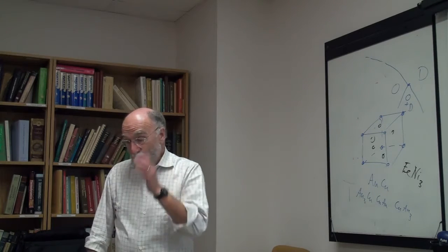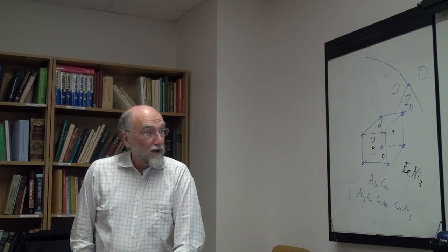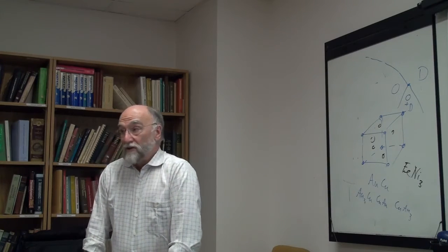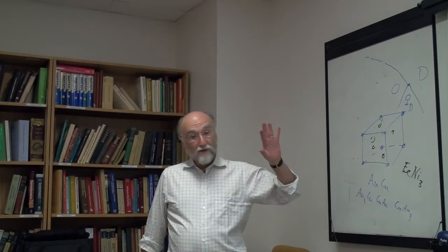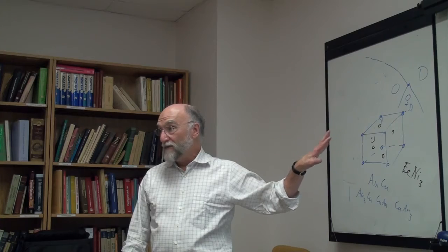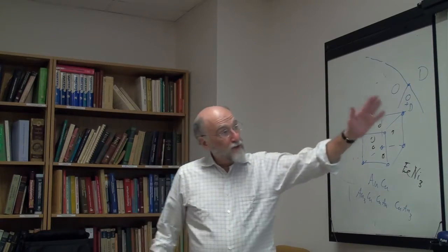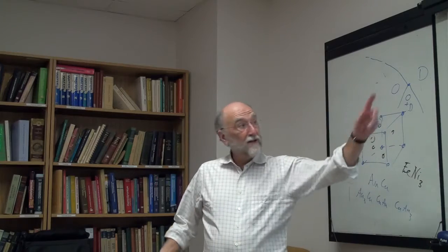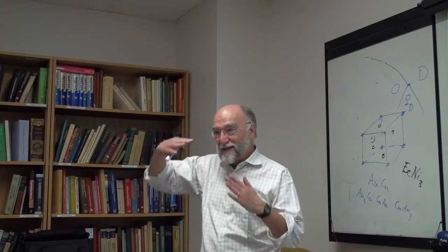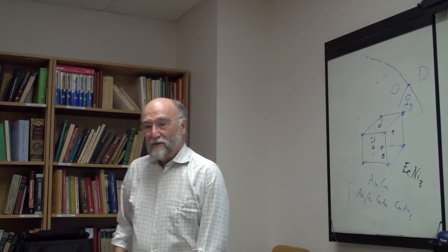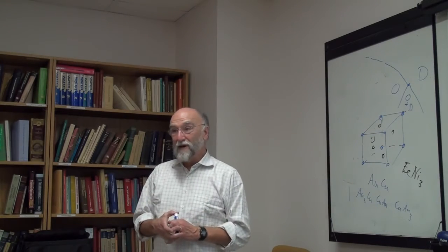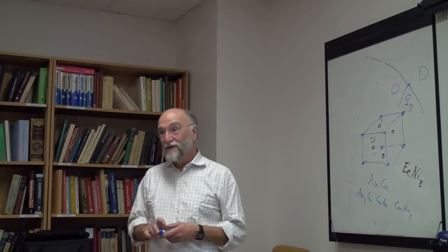Anything you will find in CALPHAD or SGTE or Thermo-Calc or whatever, and in the FactSage database, in which order-disorder transformations have been treated, they are treated using the compound energy formalism, as we do the Bragg-Williams approximation to the compound energy formalism, which is basically what you did in the exam question and what I did here on the iron nickel, with just a whole bunch of terms in order to make the thing fit. You read the papers, they talk about the terms having meaning. I'm not sure. You just force the thing to fit. But I'm not sure that the terms have much physical significance.